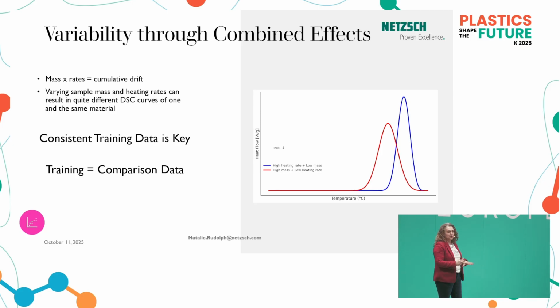So consistent training data is key, and I think that is not just from DSC data. We have that in mechanical testing. The speed at which you pull has an effect on your results, and that's why, in my personal opinion, after doing this now for quite some years, we can't just data mine technical literature, because we hardly ever get all the information we need to categorize the data and say the DSC data we can use for training or not. So we really have to create good data, and I think we heard that in other talks as well. I'm just talking about a specific data problem. And the training data and the comparison data need to match. So what you want to analyze, the unknown mixture, also has to be measured with 10 Kelvin per minute and 10 milligrams of mass.